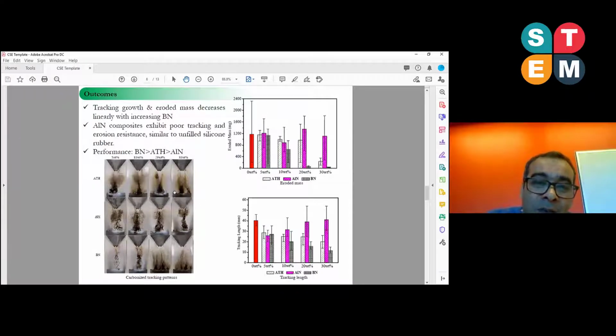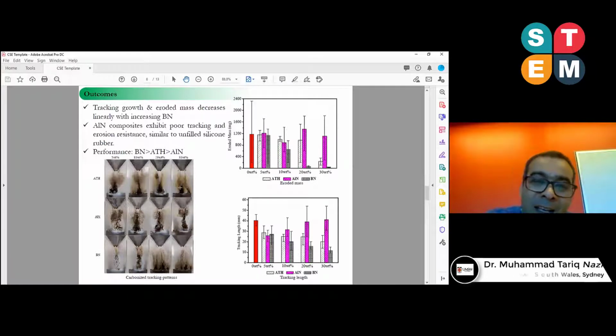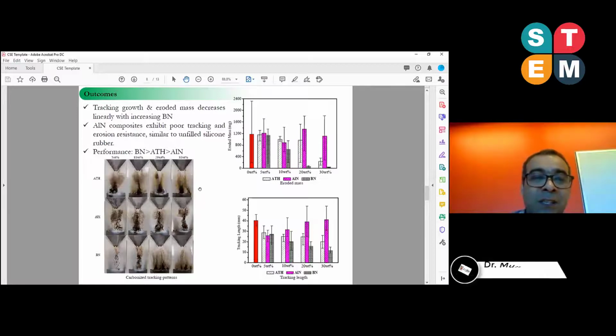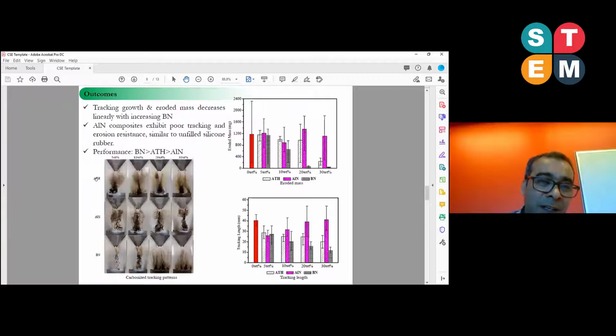Here's the top electrode, here's the bottom electrode. This is the carbon tracking, that path is showing the carbonized tracking. We don't want any tracking because it acts as a conductor, so it reduces the insulation properties sharply. We don't want any tracking on the insulation. So with the three different fillers, ATH, AlN, and BN, we compare the performance. And here we look at the eroded masses.